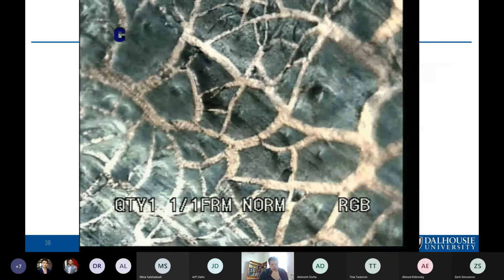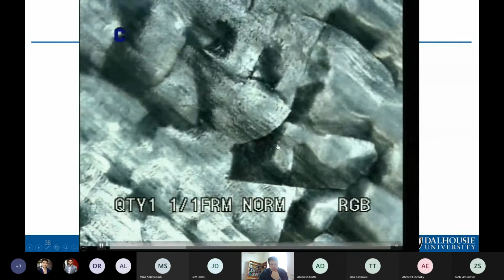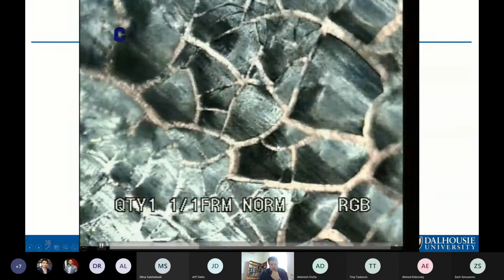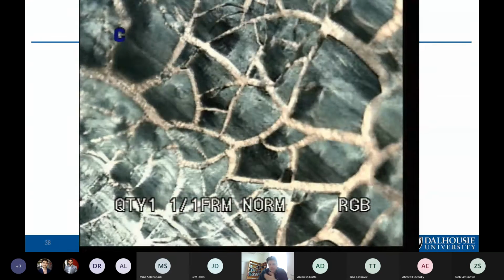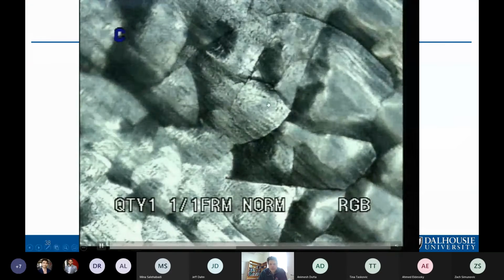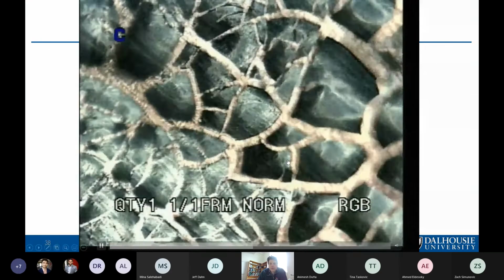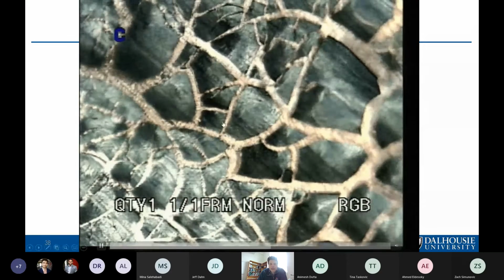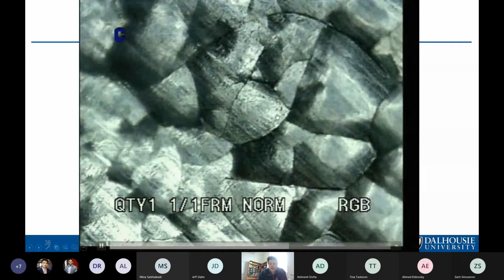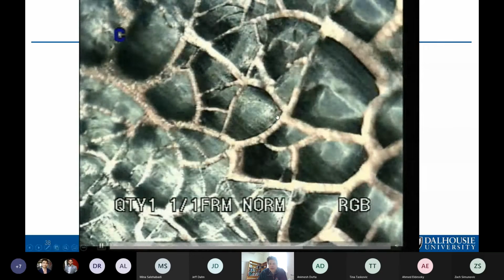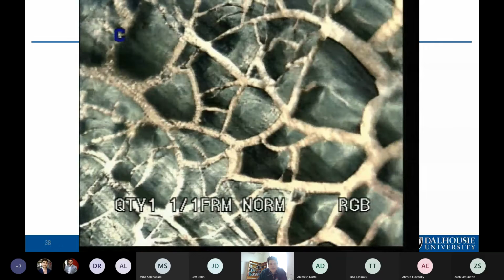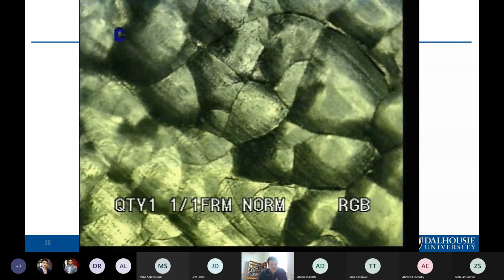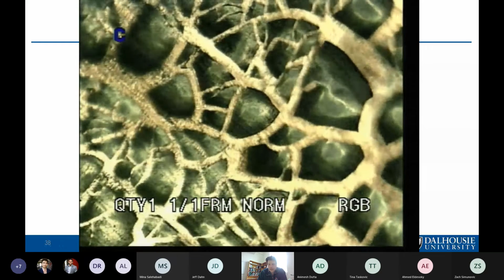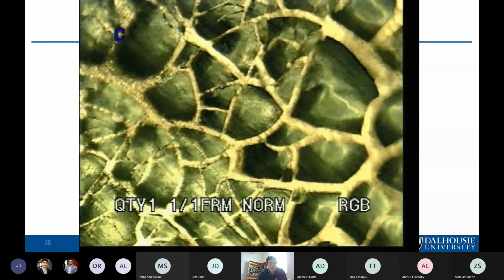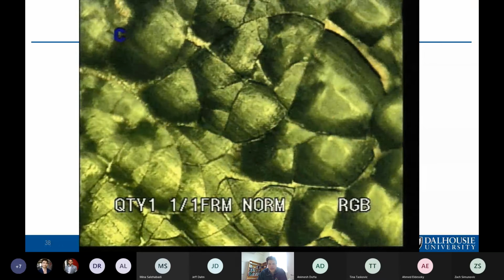So you can see that it lithiates again and goes back to where it was, and it's highly reversible. Of course, in a composite coating now, you've got a billion moving parts that you've got to hold on to, and you can see that this would tend to disrupt any SEI layer, which is an issue in cycling. But nevertheless, that's how you get reversibility of the material itself.